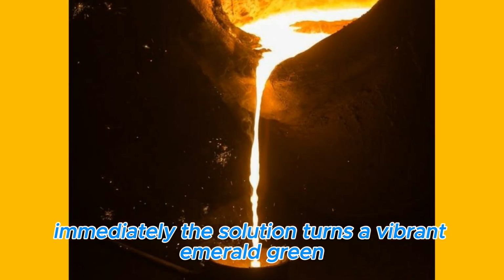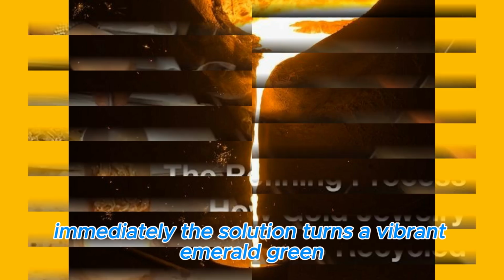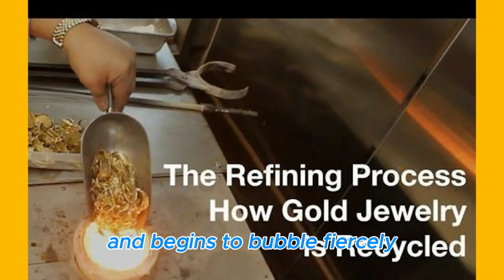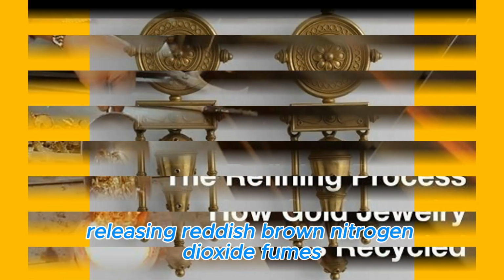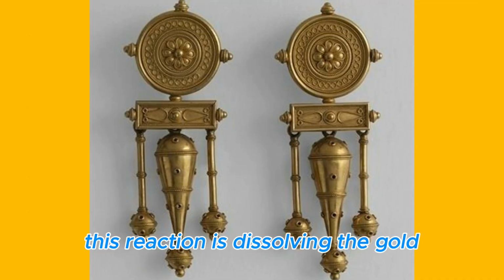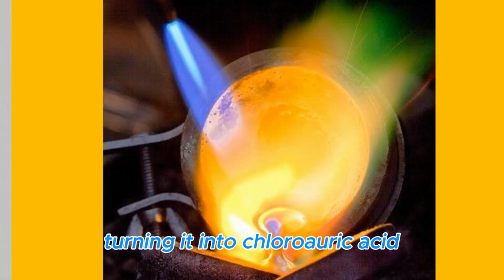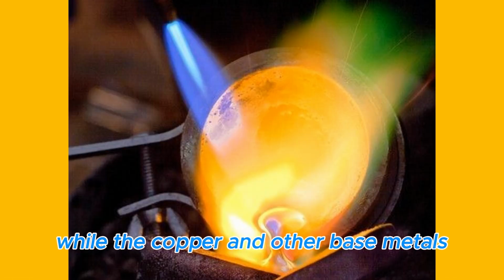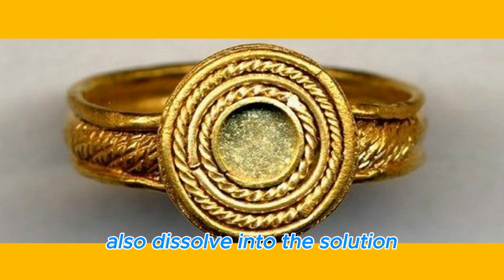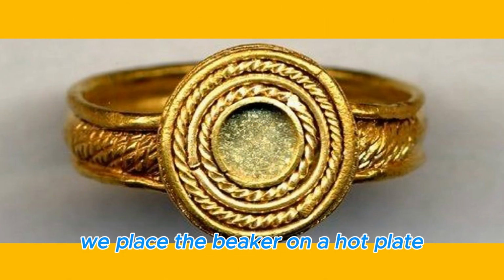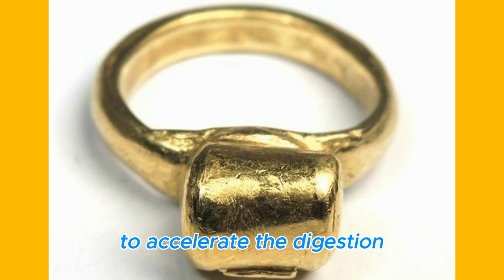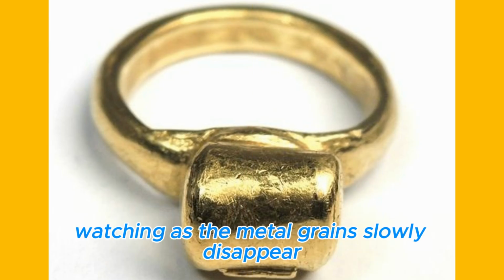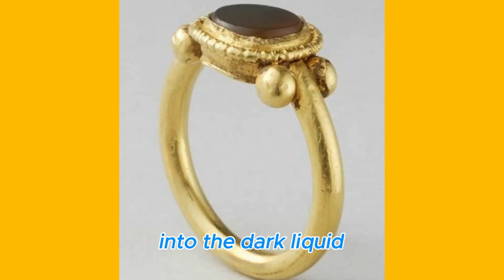Immediately, the solution turns a vibrant emerald green and begins to bubble fiercely, releasing reddish-brown nitrogen dioxide fumes. This reaction is dissolving the gold, turning it into chloroauric acid, while the copper and other base metals also dissolve into the solution. We place the beaker on a hot plate to accelerate the digestion, watching as the metal grains slowly disappear into the dark liquid.